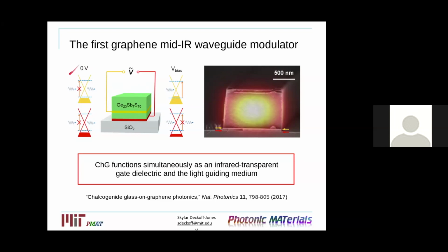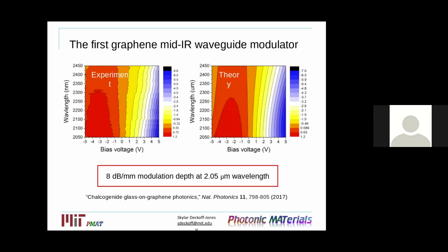And when we apply no bias, the Fermi levels of our graphene are tuned such that we get no absorption. And then by applying an appropriate bias, we tune the Fermi level so that we can then absorb photons in the centrally located layer of graphene. So not only does this enable this structure, but the chalcogenide glass also has slightly stronger interaction with the graphene, as it's not just on the very surface of the waveguide. And this shows the experimental and theoretical modulation depth for this modulator. We see that we have quite good broadband modulation over nearly 500 nanometers of the mid-infrared spectrum.